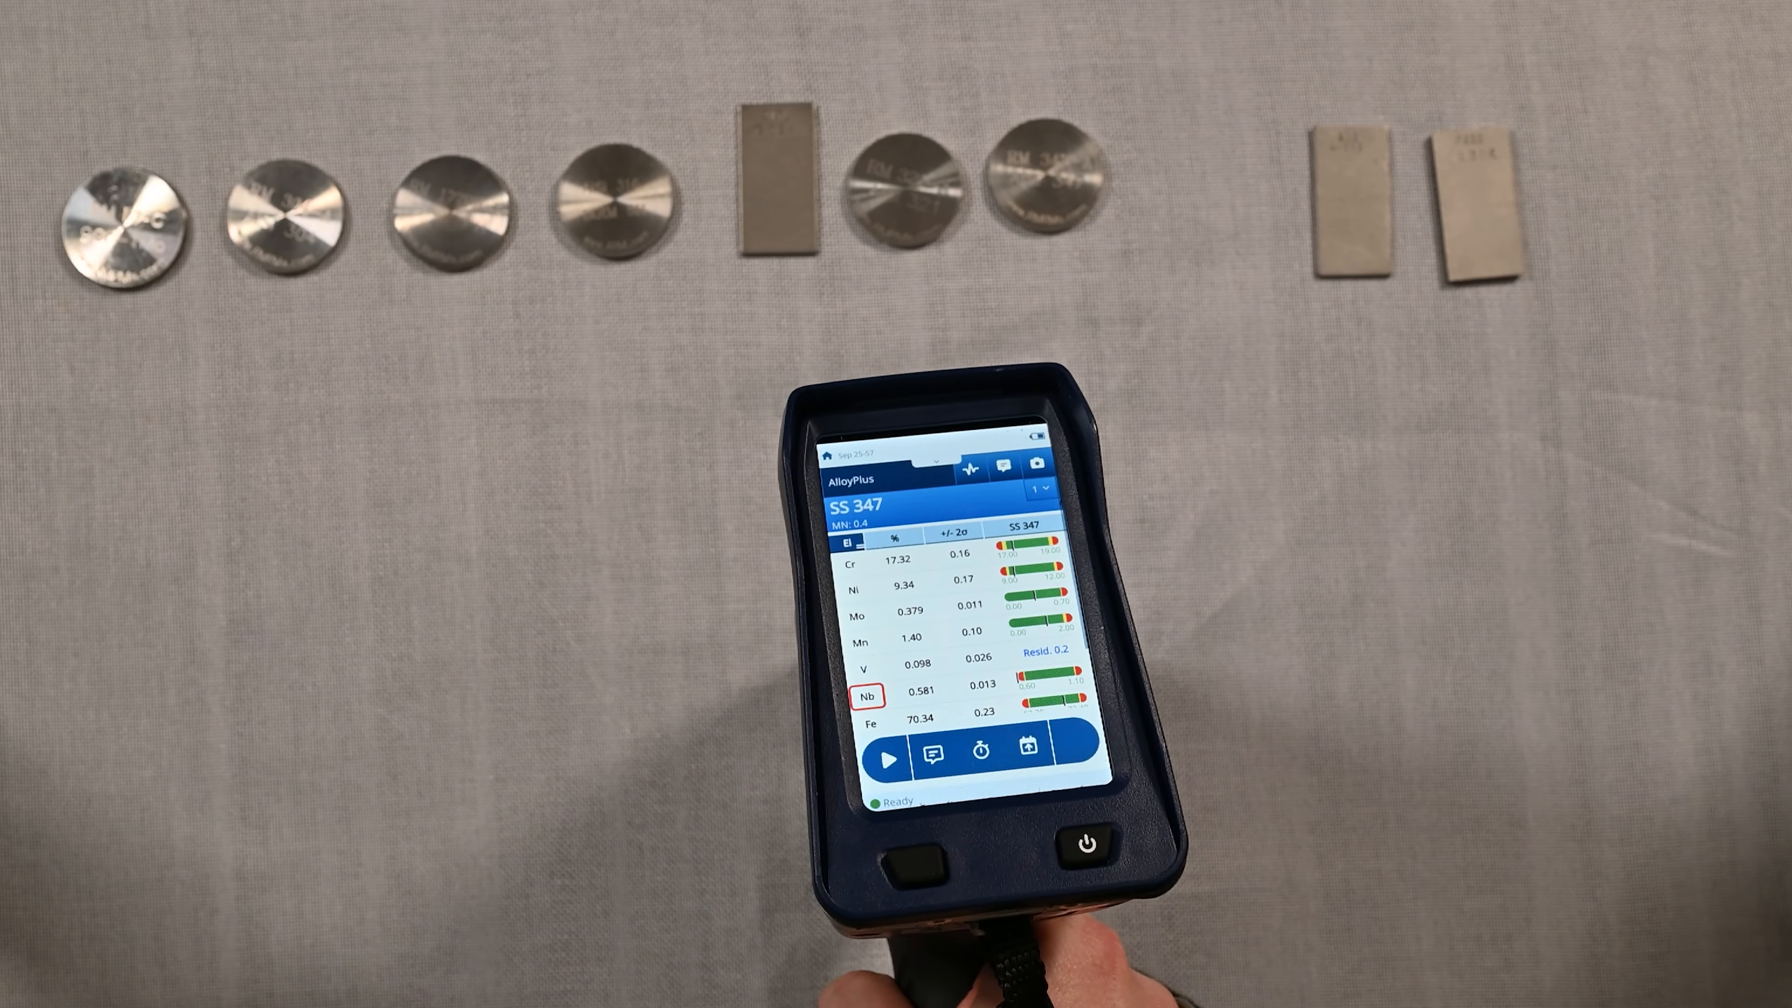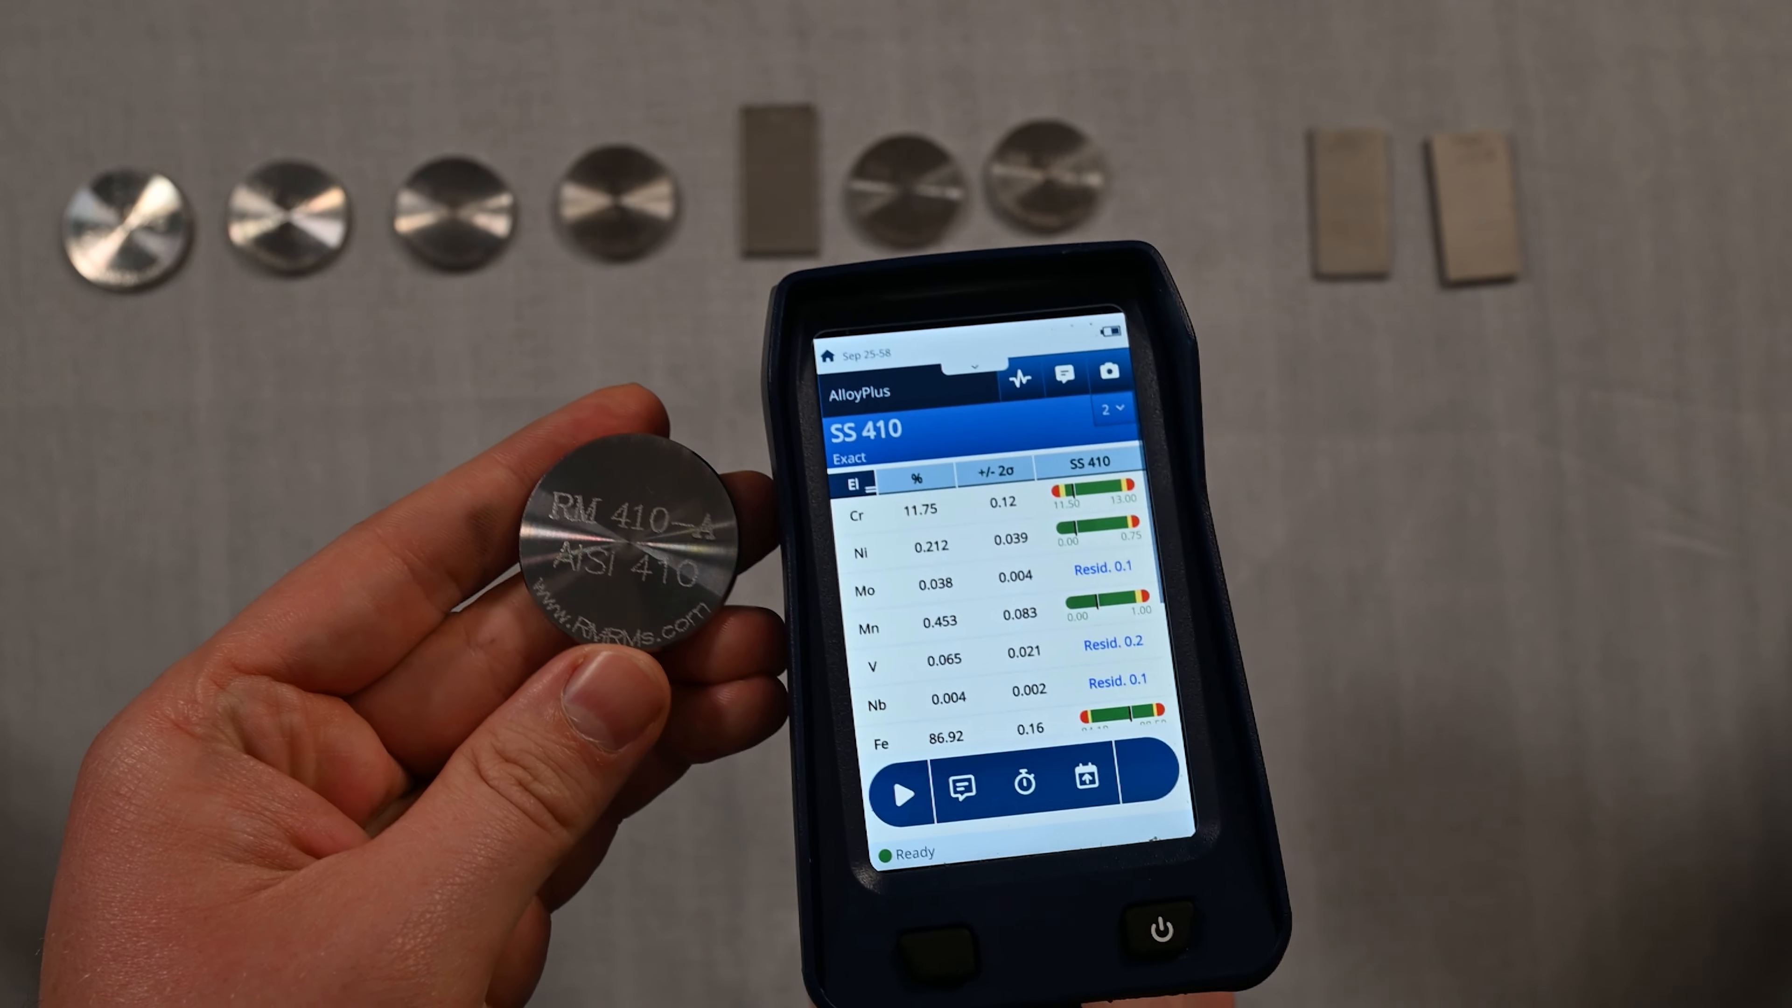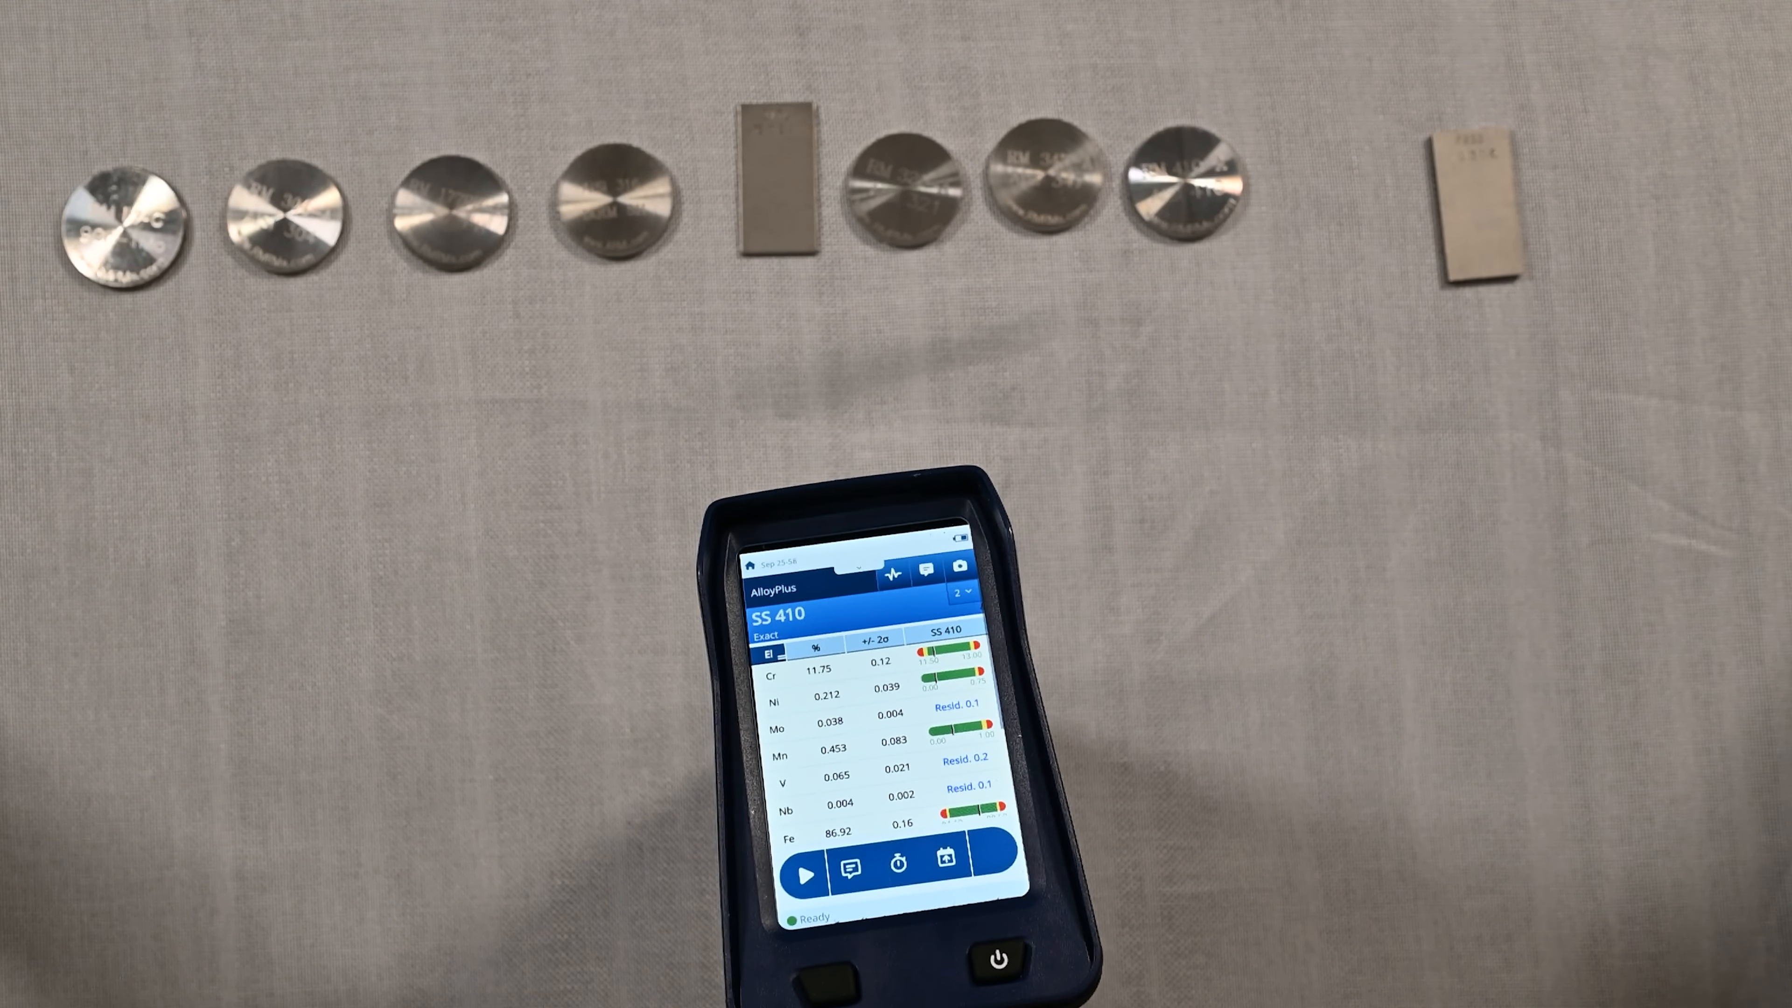Now we're going to go down in alloy content. This is a 400 series alloy, and this is an alloy where there are some other alloys here that can convolute this, specifically for the 410 series or 420 series - they can be mixed up pretty easily. But you'll see here we were able to identify 410 with no problem. You'll see that the chrome is at 11.75%, but that nickel is way dropped down to 0.212%. That's pretty low. It makes this alloy much more economical because the nickel actually adds a lot of cost when you're producing the alloy. Nickel's expensive for an addition.